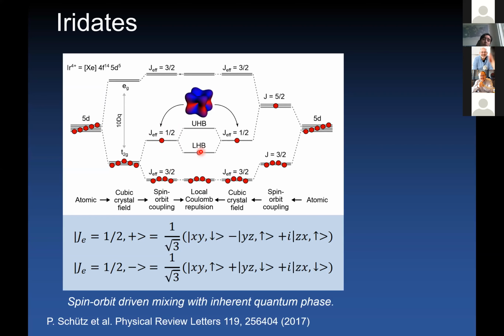So if you add Coulomb correlations in the system, you can split the electronic structure into a lower Hubbard band and an upper Hubbard band, and realize a system that goes from a metal to an insulator. So importantly, these J effective 1/2 electronic states are an entanglement of orbital and spins, where you involve different orbitals and different spins in the superposition. And I would like to stress the fact that in this superposition you have an imaginary component. So this spin-orbit driven mixing causes your system to have a quantum phase that is very important for the physical consequence,